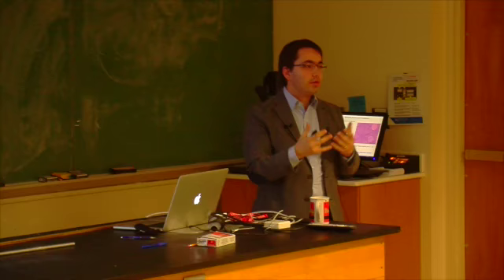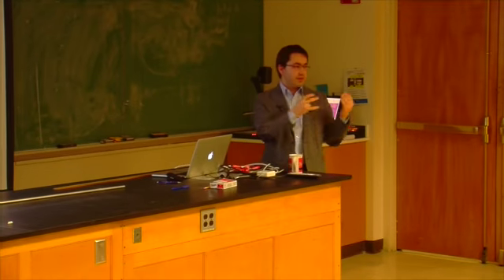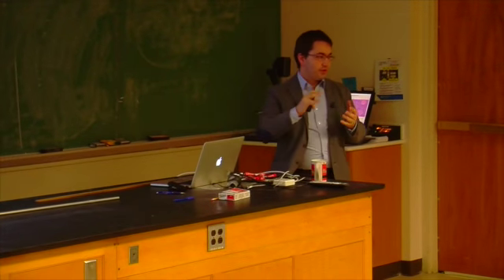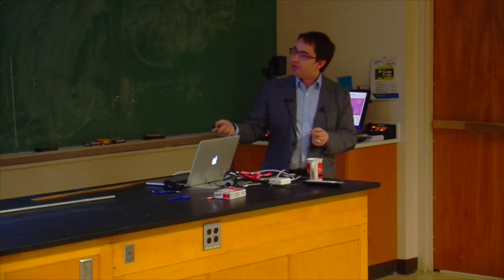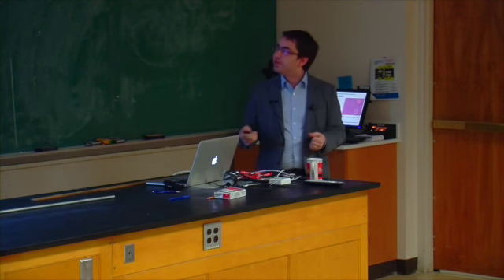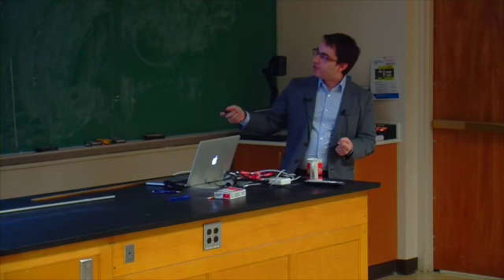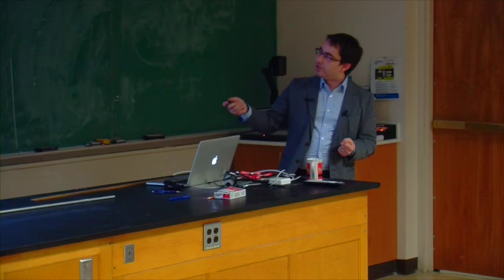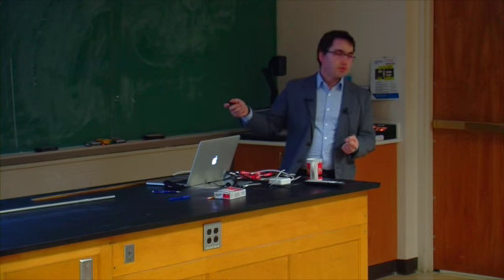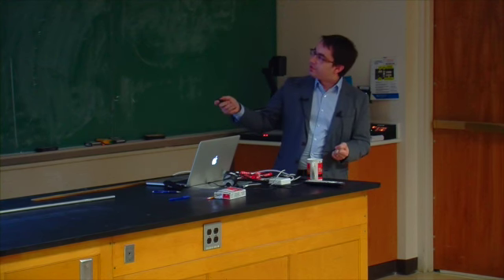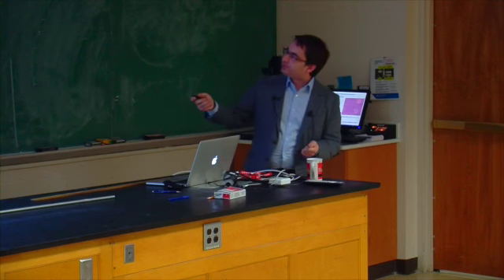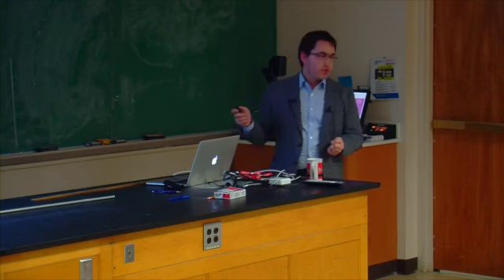And so when we introduce this misfit energy and we make a competition between elastic energy inside each layer, which doesn't like to be modulated too much, but nevertheless it tries to optimize the overall energy, then we get patterns like this, where we have these triangular patterns between the AA sites that are really unfavorable. Here we have these regions where we get the nice, favorable staggering over a large domain, and then between those domains we see transition regions which look like walls. This compares to the picture I was showing earlier, where we have large domains with perfect alignment, and in between them we have these walls arranged in a triangular pattern.